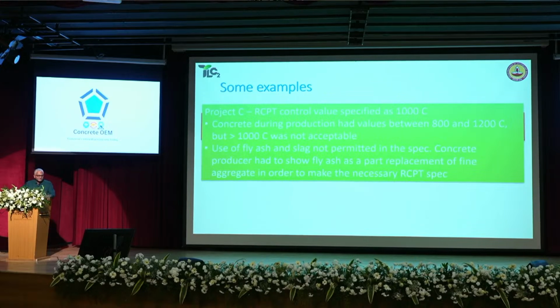In this project, Project C, the RCPT, Rapid Chloride Permeability Test, Coulomb charge passed value, control value was specified as 1,000 coulombs. That means any concrete supplied needed to have an RCPT value of less than 1,000 coulombs. But the contractor was not permitted to use fly ash in the concrete mixture, okay? Because if you've worked with RCPT tests, you'll know that any ordinary Portland cement concrete mixture of a grade of 40 to 50 megapascals is not going to get you 1,000 coulombs. Unless you have a very, very low water cement ratio in a clean concrete mixture, you'll not get that. You have to use siliceous supplementary cementing materials like fly ash.